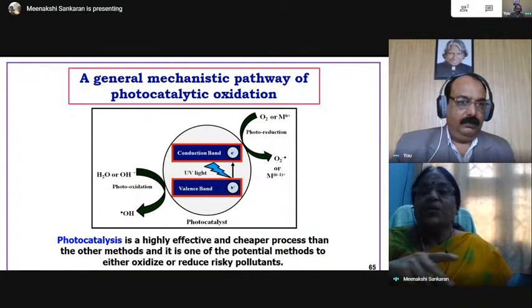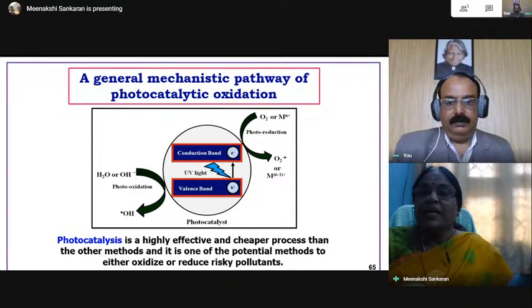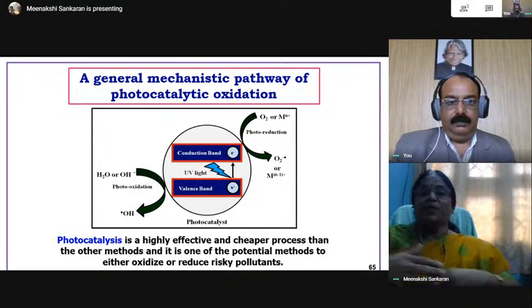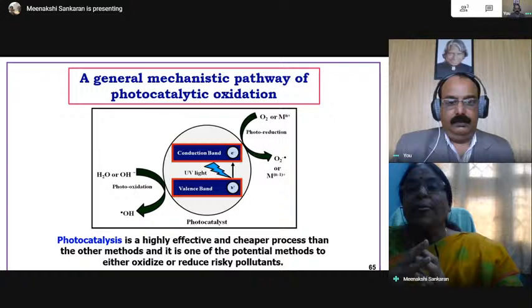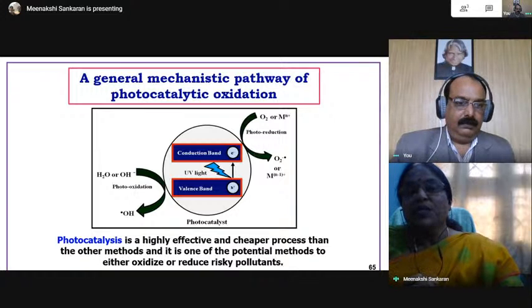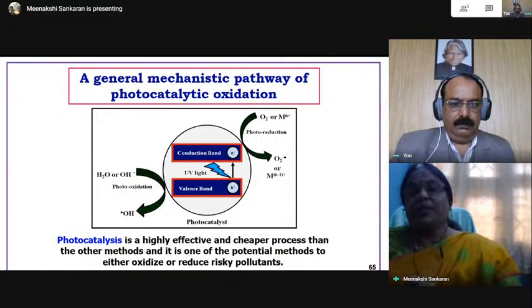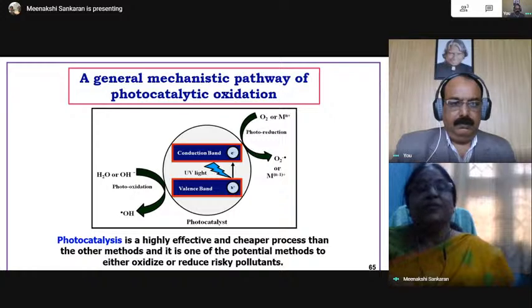In addition, these oxygen radicals reduce, for example, chromium. Chromium exists in two forms, chromium 6 plus and chromium 3 plus. Chromium 6 plus is much more toxic than chromium 3 plus. This oxygen radical will reduce chromium 6 plus into chromium 3 plus, which is less toxic compared to chromium 6 plus. Therefore, we have used this photocatalytic oxidation method for removing dyes as well as chromium 6 from effluents.